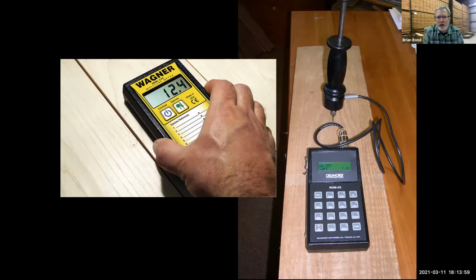What you have to be aware of is that these meters do have limitations. So they tend not to be very accurate above 30% moisture content, and they tend not to be very accurate below about 6% moisture content. And so you might say, well, if it's 6, why would I worry about that? Well, for machining purposes, if it's below 6, you want to know what it is. It doesn't glue well below 6, it doesn't machine well below 6. You've got problems there, as well as if it's too dry.